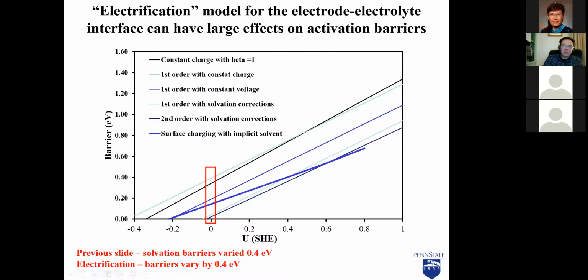And you can see if I look at one voltage here again, I get an activation barrier that varies from about 0.4 eV down to about 0. So the previous slide showed you that explicit solvation and implicit solvation can vary the barrier by 0.4. Here I show you that essentially the electrification model can vary the barrier by 0.4 eV.